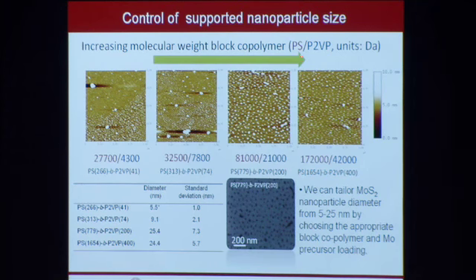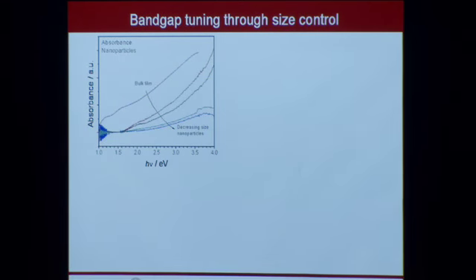So we can increase the weight of the block copolymer and get larger particle sizes out. These are AFM images up here, confirmed by SEM images. And you can see the range of nanoparticle sizes we're looking at: 5.5 nanometers, 9 nanometers, and then a couple that are around 25 nanometers in size. So now that we've got these supported, we want to measure UV-vis absorption on them.